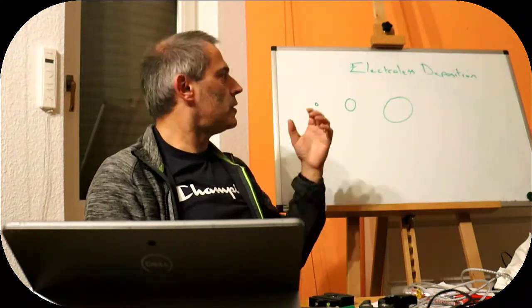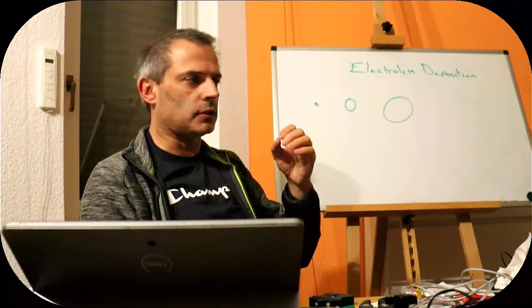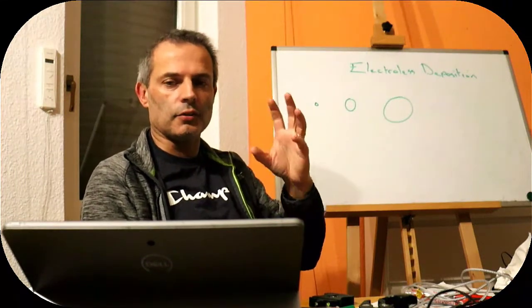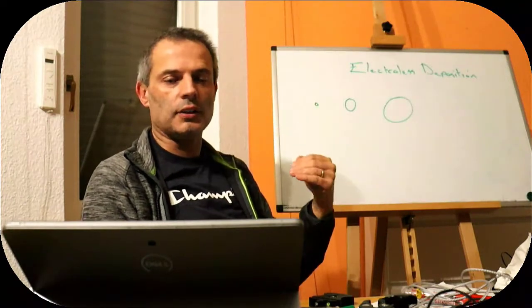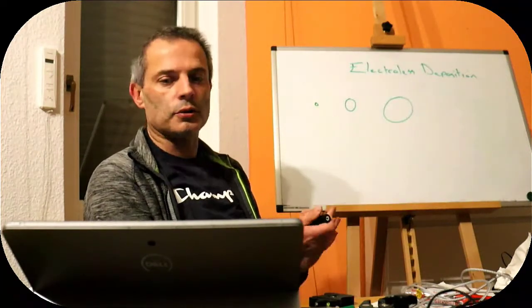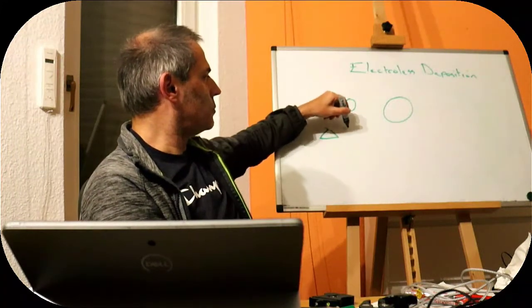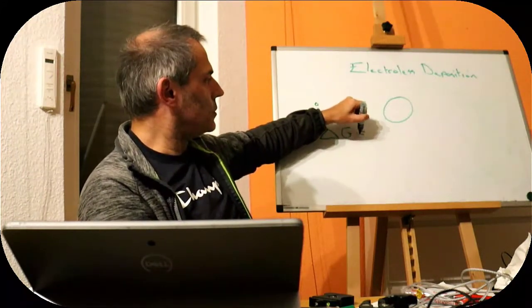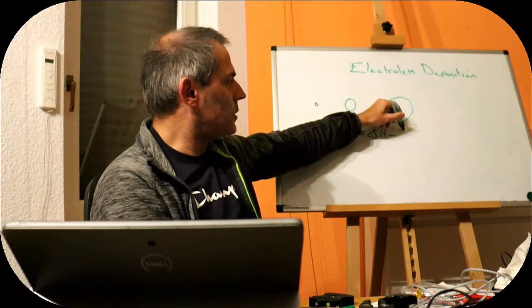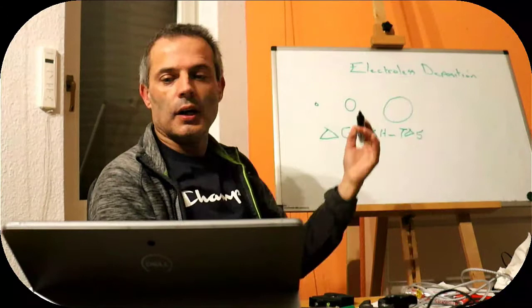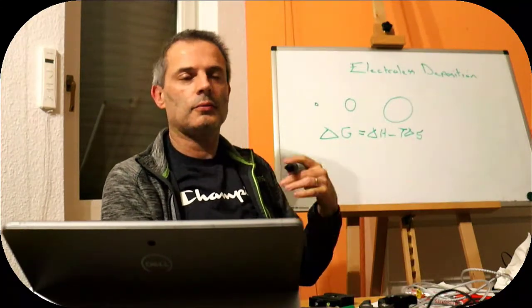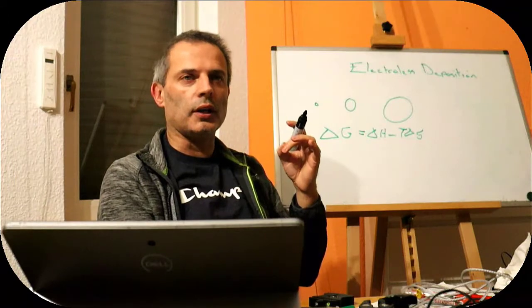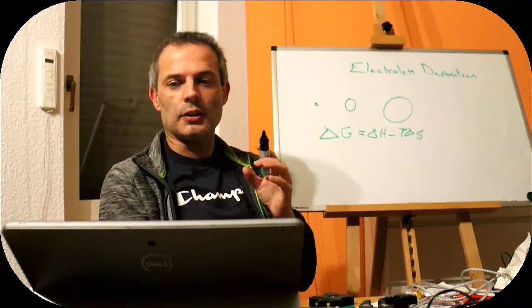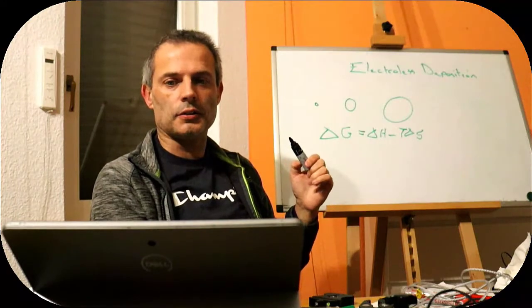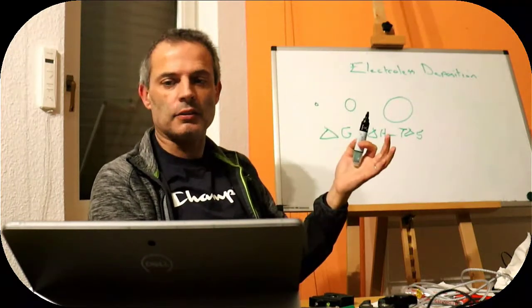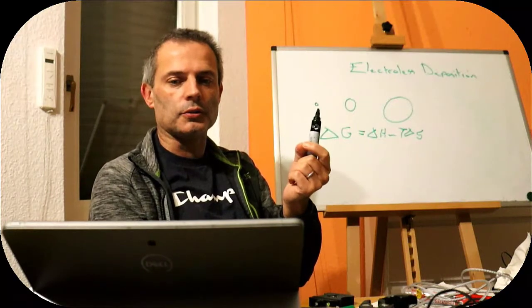But we have an advantage, that generating a new particle is difficult, because a new particle has a very high surface area to volume ratio, so it is comparatively difficult to do that. And if we look at the process, we can see that the Gibbs free energy is equal to delta H minus T delta S. It's the same as always, but when we do this for bulk materials, we ignore a term for the surface energy, the Gibbs free energy of the surface, and that is comparatively large for starting the particles off.